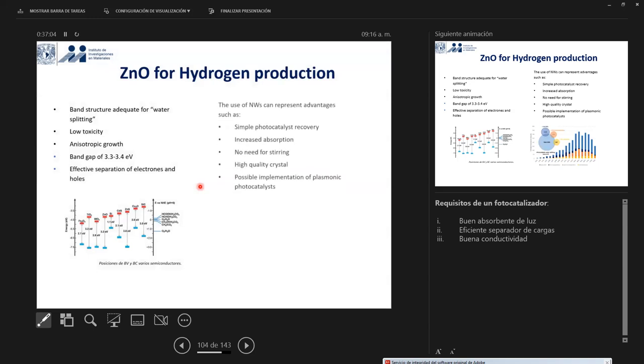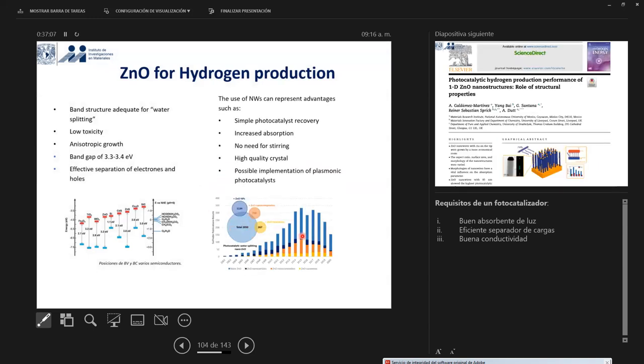Now talking about nanowires. In nanowires also, we did some studies. In the catalysis part, as a whole, zinc oxide has had like 3,000 to 4,000 articles in the recent 5 years. But if we go to nanowires, the studies are quite limited. And the benefits of nanowires are quite surprising actually, because in this case, we have photocatalyst recovery. We can have enhanced absorption, no need for stirring, high crystal quality, and we can have implementation of plasmonic photocatalyst if we have gold on the tip of the nanowires. So this material is quite new. The studies are limited, but they have quite some advantages.